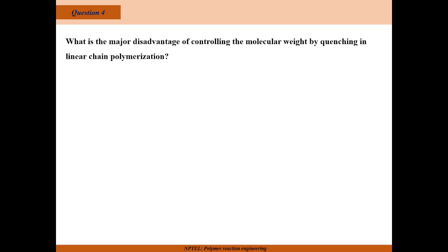Also, we can say that the polymer is not necessarily terminated, we are not terminating the polymerization. It can lead to the addition of further other functional groups, because if the temperature changes, at that particular temperature other reactions can take place and other functional groups can just add up into the chain. Thus, proper control of the molecular weight may not be achieved by just changing the temperature. It may just slow down the reaction.